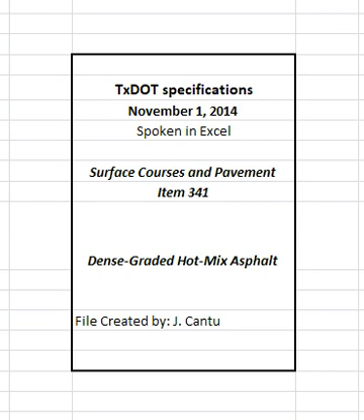If the engineer's laboratory molded density on any sublot is less than 95% or greater than 98%, take immediate corrective action to bring the mixture within these tolerances. The engineer may suspend operations if the contractor's corrective actions do not produce acceptable results. The engineer will allow production to resume when the proposed corrective action is likely to yield acceptable results.